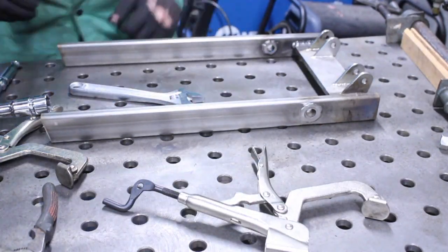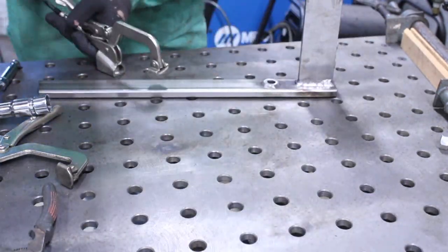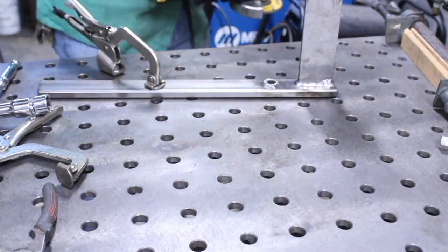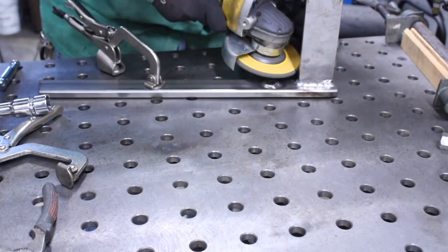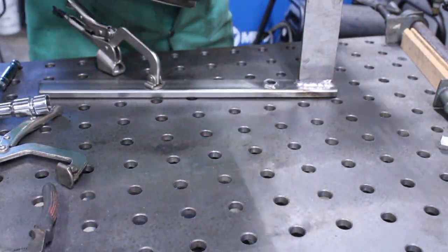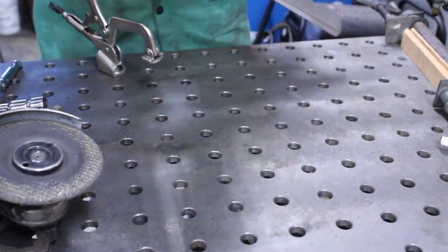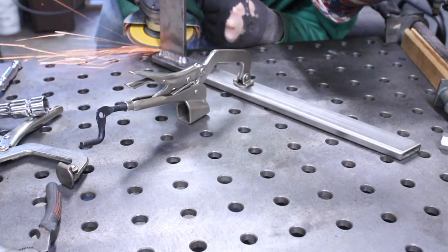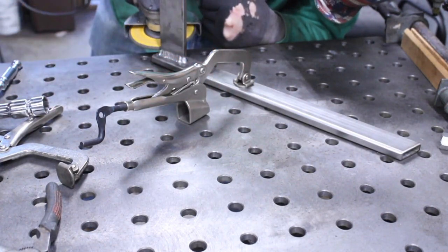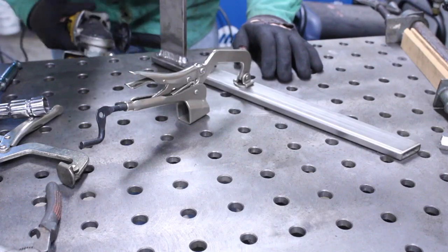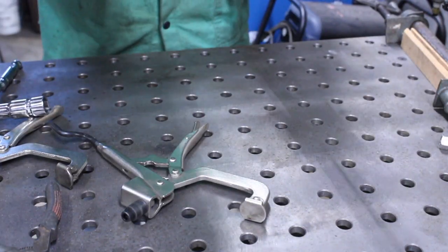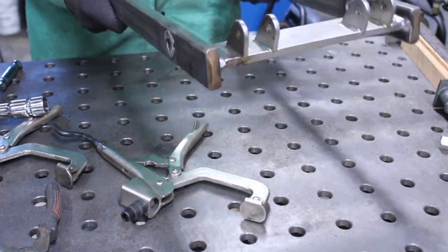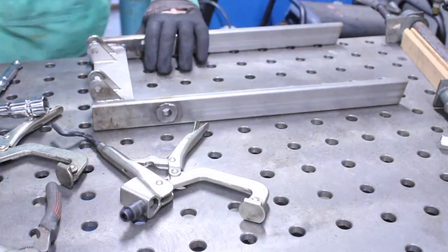Back to the project. With TIG welding, you have this wonderful ability while you're finishing a weld to backstitch over the end of said weld and to avoid a crater crack. With MIG welding you can't really do that, so you'll see me here, I'll pile extra at the end of the weld and then grind it down so I don't get that crater crack.